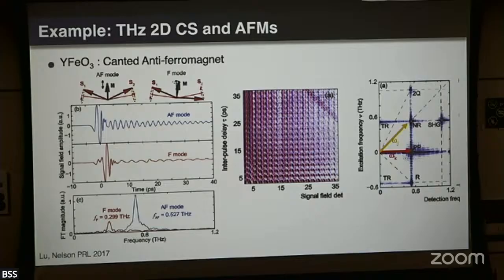You can see that there are some of these peaks that we've already discussed. There's the non-rephasing peak, there's the rephasing peak. That's the 2 quantum signal right there, so that accounts for exciting 2 magnons at a time. If you had really narrow line widths and perhaps a situation with non-collinear spins in a system like this that were even more pronounced, you might see that the frequency of this peak was displaced from the ones below, which would correspond to the hardcore interaction of 2 magnons, which is a very interesting thing to measure. I mean, you can't measure the interaction of 2 magnons in any other way, right?